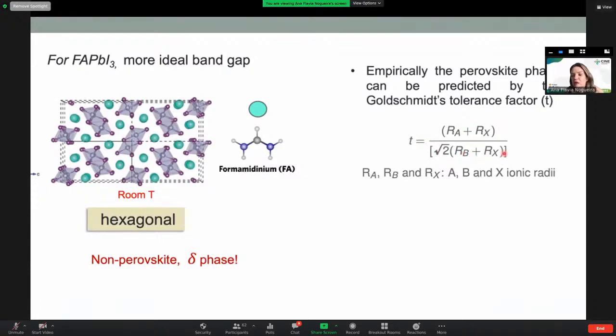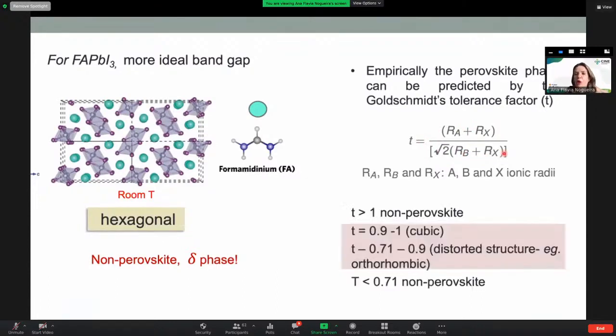When you do this calculation, when the tolerance factor is higher than 1, which is the case here because formamidinium is a quite large cation, we have a non-perovskite phase. Or when T is less than 0.7, it is also a non-perovskite phase. That's the case when you replace formamidinium with cesium only. With cesium only, it is also a non-perovskite, non-cubic phase.